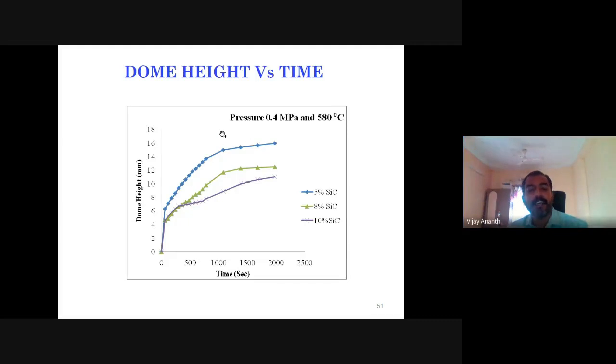Normally, once we initially open the air, the initial formation is very much higher. Initially the air is touching this component, so the first 6 mm is formed very quickly. Then it proceeds step by step, for nearly 2000 seconds. We take 2000 seconds to form this component.